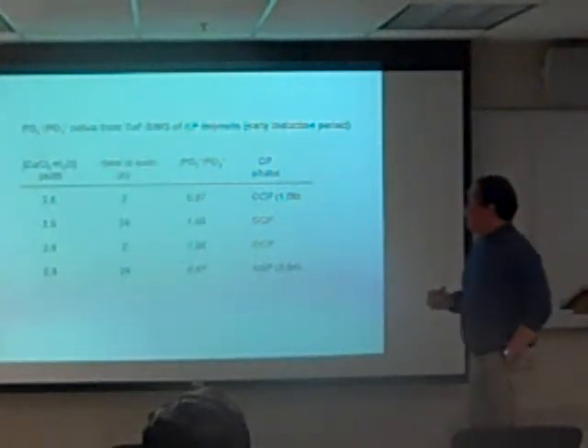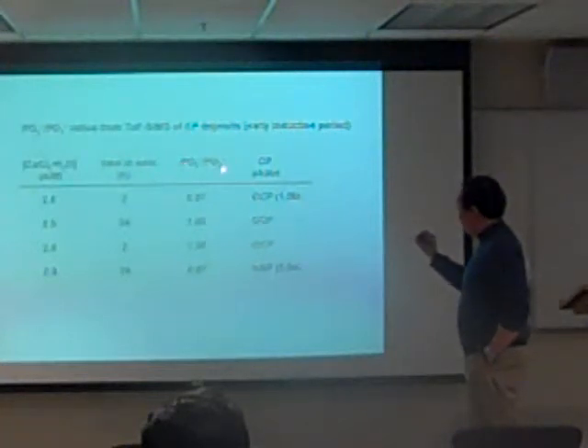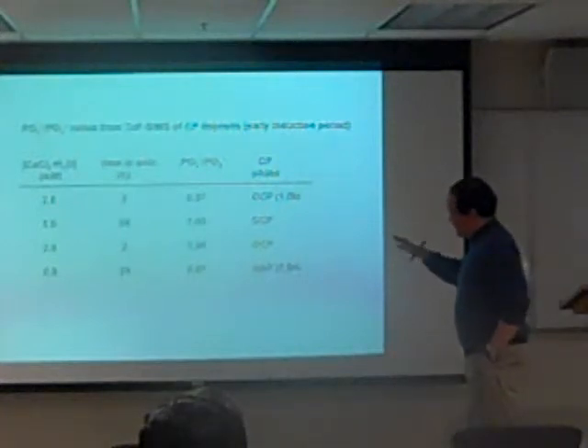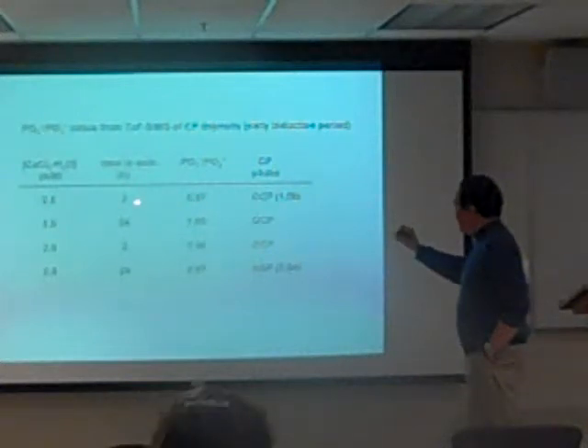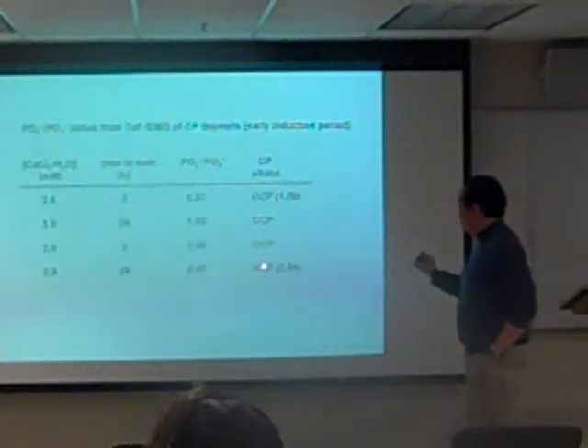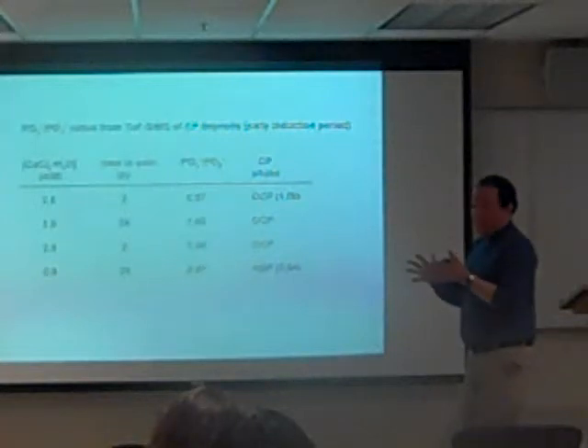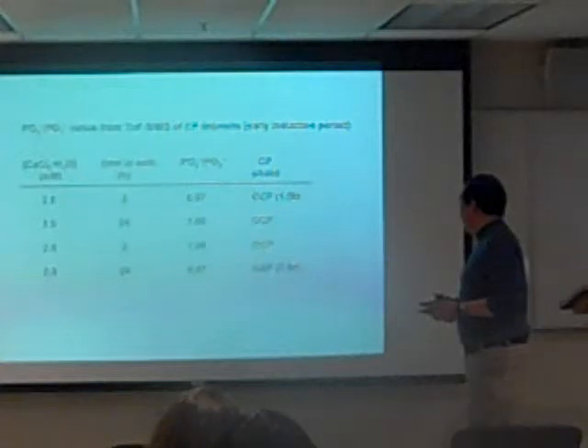Okay. So these are data from our time of flight SIMS. Again, this is noting the PO3 to PO2 ratio, phosphite to hypophosphite. And then this is at the early stages of growth. But even at these low stages of growth, we see evidence for, let's say, formation of octocalcium phosphate and hydroxyapatite. So if you just look at this, we can actually see the phase formation onto the carboxylic acid SAMs. And so that basically corresponds with what we see here and here.